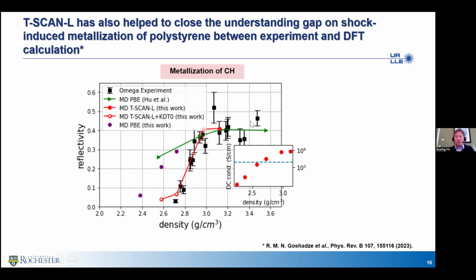Right? So for a long time, people use PBE, including myself, we get a wrong answer. You see the reflectivity turn on. If you use a PBE, it will turn on at a much lower pressure compared with the experiment. And the student Goshadze took this new temperature-dependent exchange correlation functional, which is the red line, and we eventually closed that understanding gap.